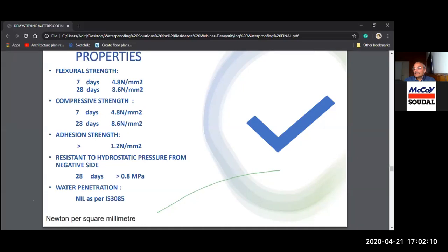properties. So the flexural strength in 7 days is 4.8 Newton per square millimeter. And see, we have seen that after applying crystalline coating, the waterproofer says, sir, it is done, there is no need to do anything after this, it does not need curing. All these coatings require curing, but the curing cannot be done using a pipe hose. It has to be done like a mist, using a back pump, sprayed as a mist. Just moisture has to be applied. There's no need to put free flow water on it.